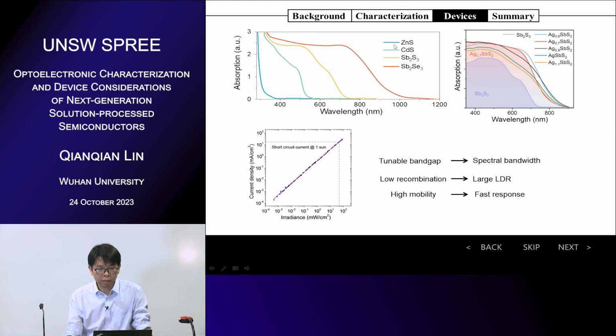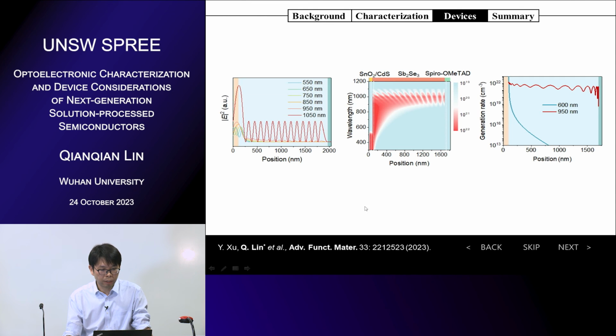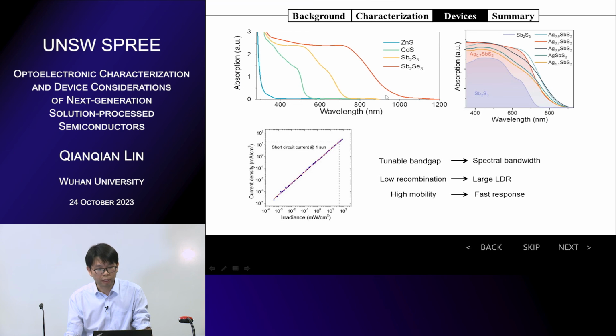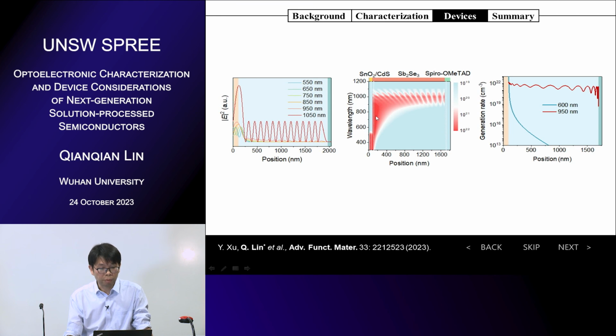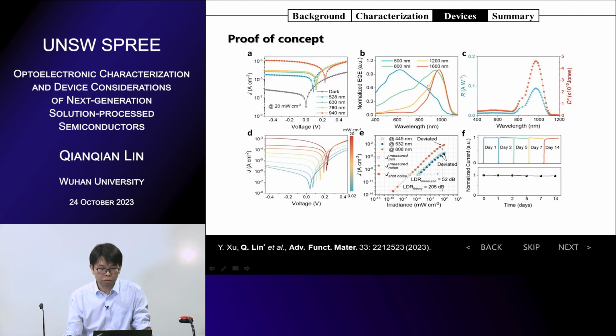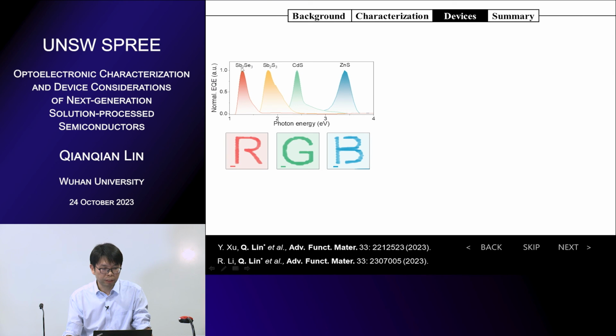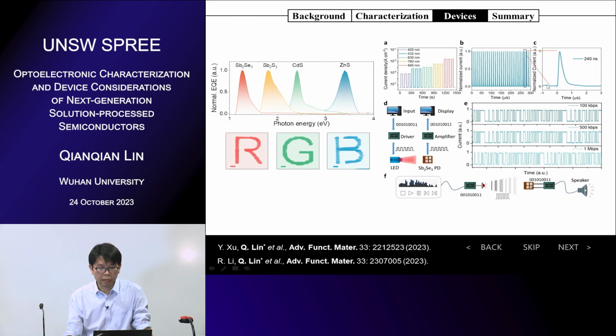And recently we also realized real devices from chalcogenides. So we use different chalcogenides, and we achieved the tuning of absorption. We also did some characterization of the optical and electrical properties, and some optical simulation as well. And we also achieved a very narrow photo response from the chalcogenide semiconductors. So we fabricated 4 devices with very narrow EQE spectra, and you can use them for imaging, and they are also fast. So these devices can have 240 nanosecond response, and we can use them for optical communication as well.